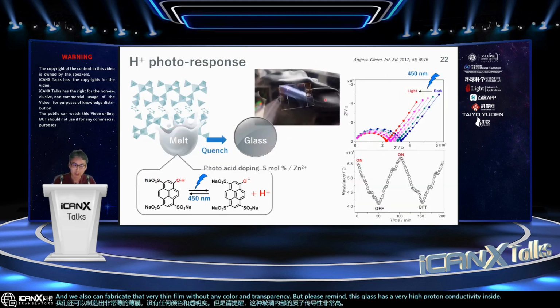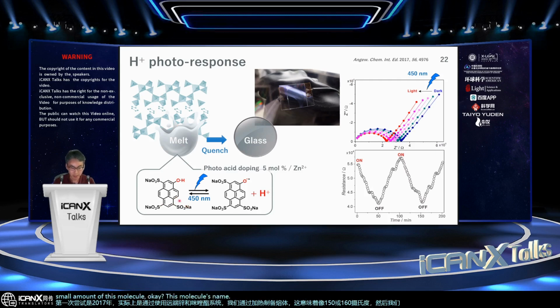The first attempt was in 2017, and by use of this zinc and imidazolate system, we prepared a melt by heating, at around 150 or 160 degrees C, and then we doped in a small amount of this molecule. The molecule's name is pyranine, which is famous for releasing a proton or catching a proton by UV irradiation, like this. So we assumed small doping of this pyranine molecule into the melt and quenched the glass. You can see the glass sandwiched between 2 ITO electrodes, totally transparent, with good distribution of this pyranine in this MOF glass.